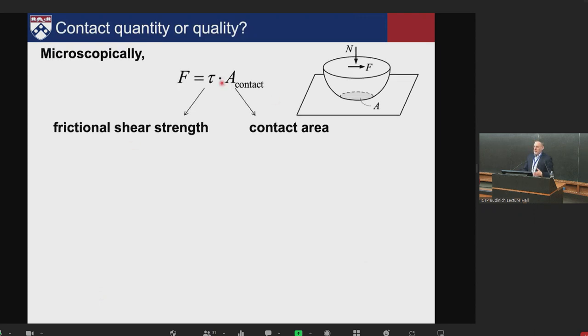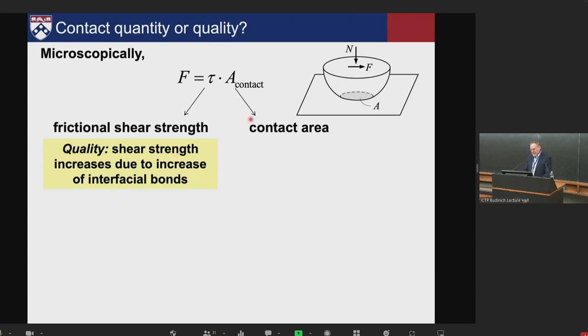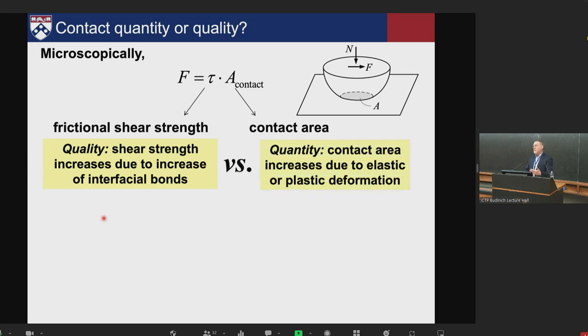And in particular, to what extent does the force you measure depend on how big an area of contact you have? Or how much does it depend on the frictional shear strength, the force per unit area that you have in the single asperity? And you can somewhat crudely, but I think still meaningfully, divide these two quantities, the shear strength and the contact area, into two concepts. The shear strength is like the quality of the contact. If you have more interfacial bonds, if you have a commensurate interface, if you have maybe contaminants, that can give you higher force per unit area. But also if you have just more atoms in contact, each one of those interfacial atoms is pairing with something across the surface, and that can increase friction, just elastic deformation, plastic deformation. Separating these out, I think, is important.